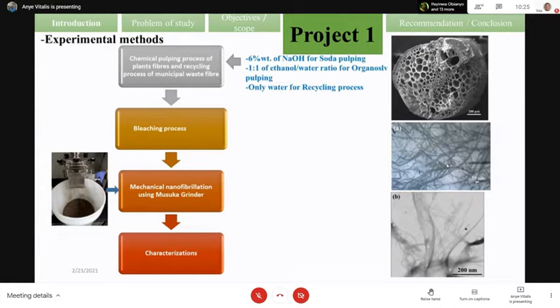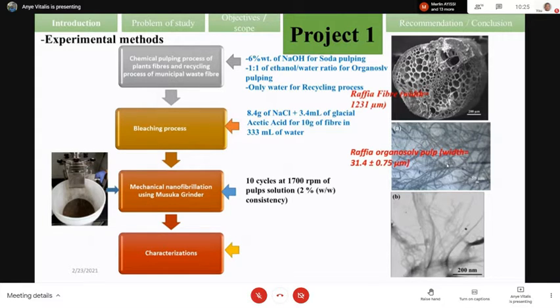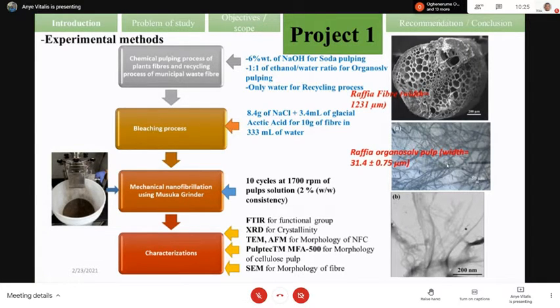So what is the experimental method? We are using a cellulose pulping method, using soda pulping and organosolv pulping with ethanol. For the recycling process, we use only water. Then we use a bleaching process, which helps us reduce the residual lignin, using sodium chloride and glacial acetic acid. For the mechanical step, we use mechanical nanofibrillation with the Masuko grinder at 10 cycles. The obtained cellulose nanofibers have been characterized mechanically, chemically, physically, and morphologically.